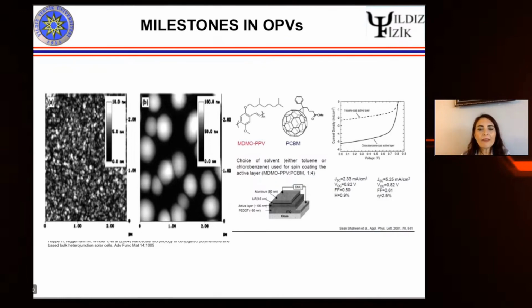But of course, we realized that for each polymer, or whenever you start with a new material, you have to start from scratch, and you always have to do these optimization steps for each material from the beginning. So for the PPV and PCBM system, chlorobenzene might be the best solvent, but for different kinds of systems with different kinds of polymers and fullerenes, or maybe non-fullerenes, there can be another appropriate solvent. The reason behind these two different morphological images was this: you have two different kinds of materials, but they have two different kinds of solubility in the same solvent. Therefore, there was this phase separation.